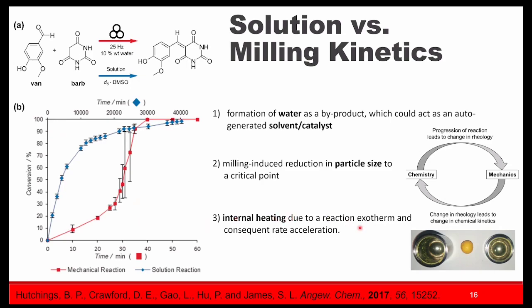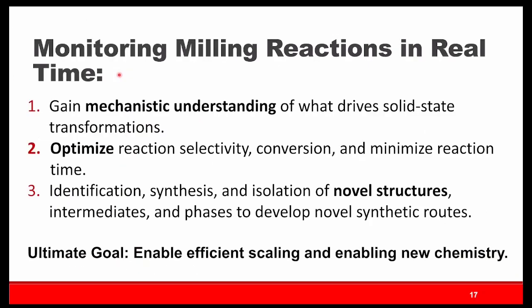And so in this case, what they ended up describing it as is a change of reaction rheology. So basically you have, again, this mechanical component and this chemistry component, and they found that this turns into a gum-like phase, and that somehow the reaction propagates much faster through there. I thought this is a really nice example of the difference that mechanochemistry and solution chemistry really are, and how kinetically different the profiles look for what is otherwise the same reaction.